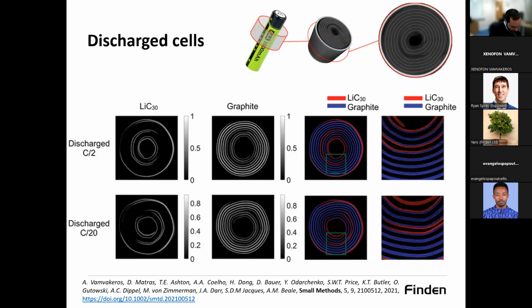And in 21, we performed the first XRD-CT experiment of a lithium-ion battery, a cylindrical one. So a real device. This comes with challenges that we don't have to discuss here, data challenges. But I wanted to show you that we had these discharged cells, so these were static measurements. And you can see, as expected, the graphite. But there are regions where you have this partially lithiated graphite, so lithium carbon 30, 30 plus.